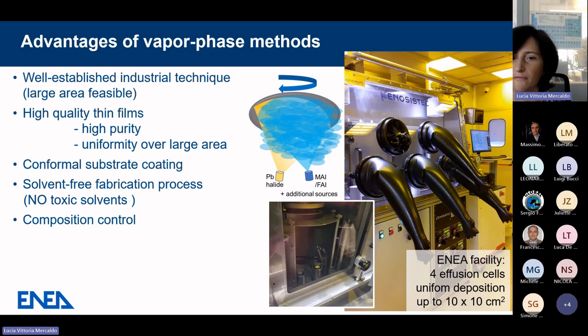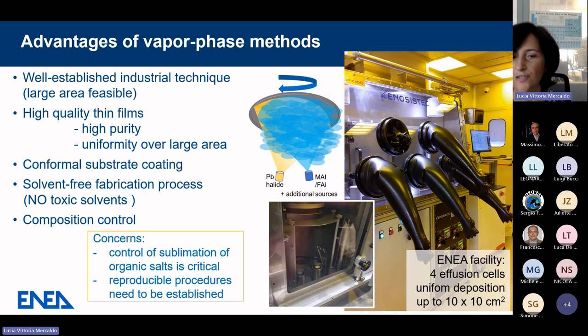It's a solvent-free fabrication process, so intrinsically it does not use toxic solvents, and it is in principle possible to control the composition of what you are preparing. There are concerns, though. The control of sublimation of organic salts is critical, and reproducible procedures need to be established.